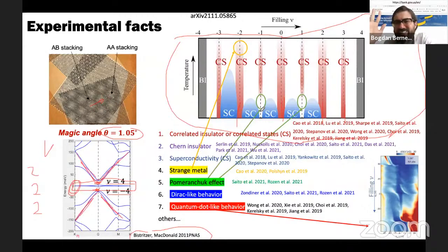Now, at every integer filling is a made-up statement. You see insulators in different samples at different fillings. Most samples see insulators at filling 2 and filling -2. So those are very clear. Now, depending on whether your sample is aligned with the boron nitride substrate or not, you can see insulators at filling 3 and -3, etc. And some samples see insulators at filling 1, etc., -1. But there are insulator features, at least, and clear insulators at some or all integer fillings of electrons.